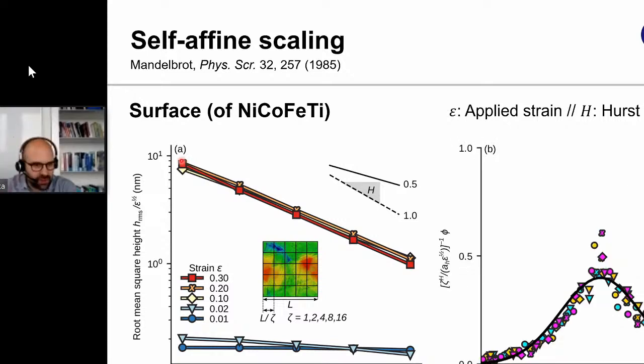This HRMS is, of course, simply the width of some underlying height distribution function. We can now look at the full height distribution function. This is what's shown on the right, and we can rescale the heights that we find. So this is the h here, rescaled by the magnification and the Hurst exponent.